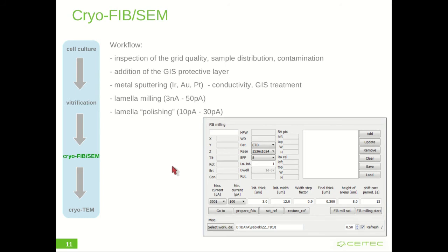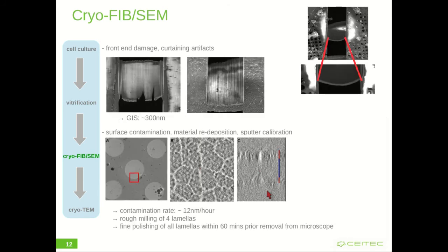For automation, we have developed and are now testing software for unsupervised lamella milling. Ideally, we want to end up with a lamella with unperturbed GIS layer on the front edge and a uniform thickness over the lamella surface. Significant sample contamination can result in uneven lamella milling and non-uniform lamella thickness, and the removal of the GIS layer can cause lamella cracking.